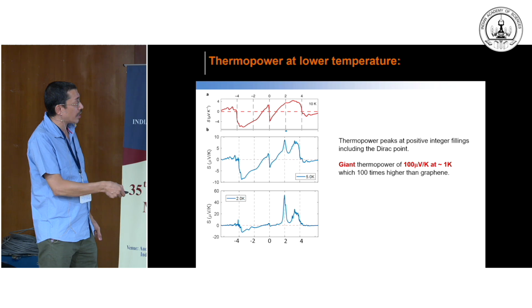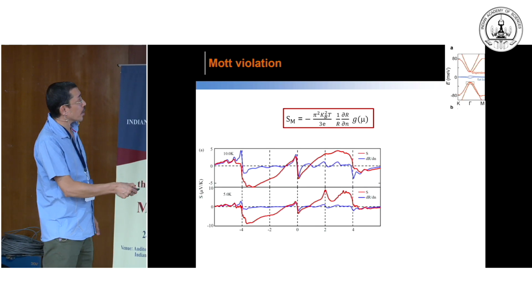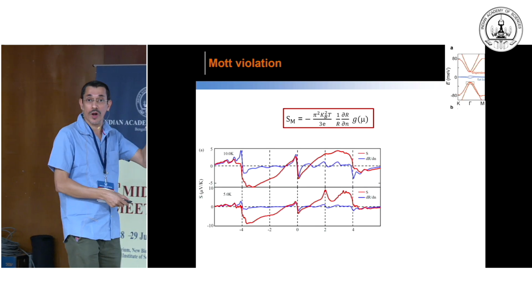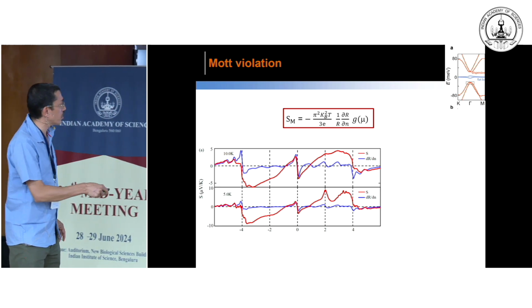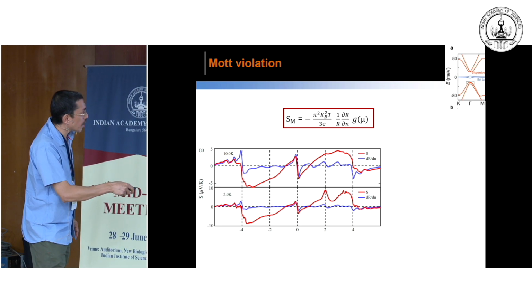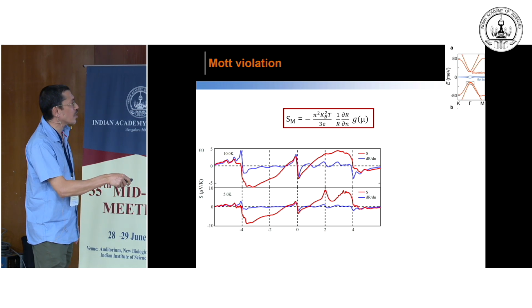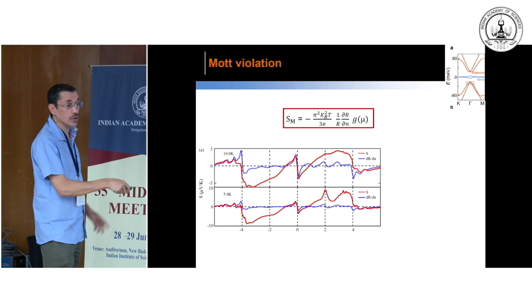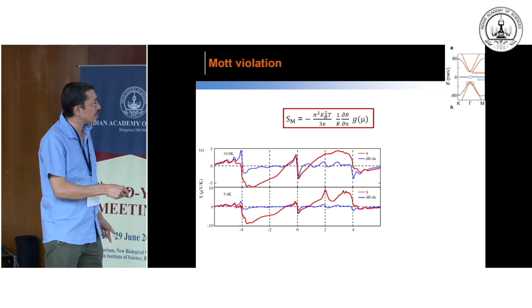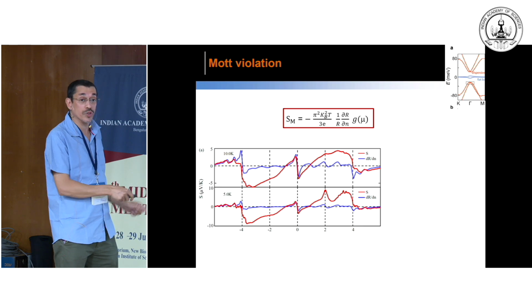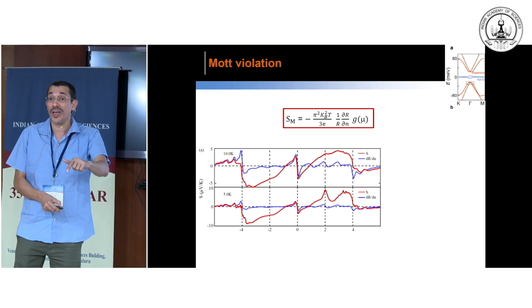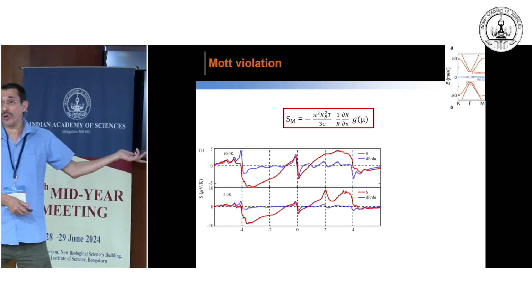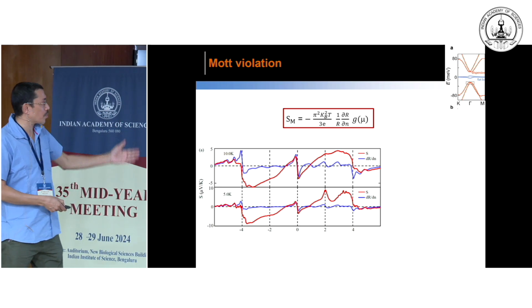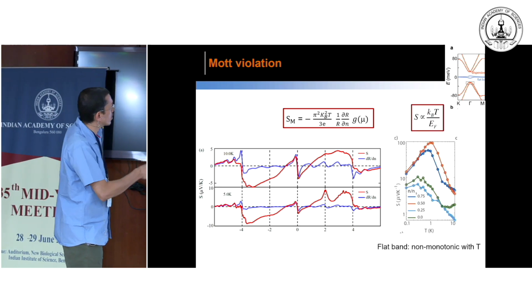to peak at this filling 2, because there is a famous Mott formula which tells you where the thermopower should change its sign. The Mott formula uses the derivative of the resistance, and is supposed to give you many changes in the thermopower features, but in the measured thermopower you have only a single crossing, so a complete Mott violation. At the resistance peak at filling 2, the thermopower is supposed to go to 0. Instead of going to 0, it shows large resistance and large thermopower. So this is a complete Mott violation.